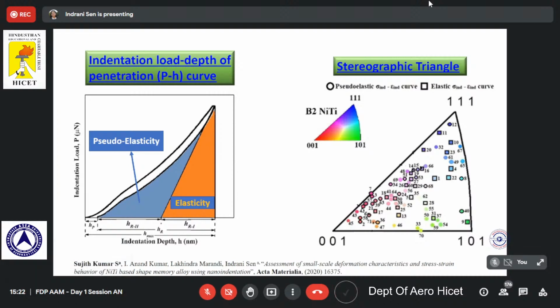So you can see the P-h curve for three of the representative orientations that I'm showing you today. So these are the HKL values, different grain orientations. You can see that for the three different cases, we see a complete difference in their P-h curve, the load versus depth curve. You can see the blue one is almost coming back to its initial phase and there is not much change.